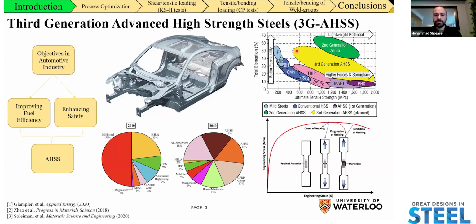Now, one of the main reasons that we are able to get the properties of third generation advanced high strength steel in terms of strength and ductility is related to transformation induced plasticity, or the TRIP effect, where we get localized transformation of retained austenite within the microstructure of these steels to martensite at the onset of necking, which inhibits the necking to higher elongations, basically.